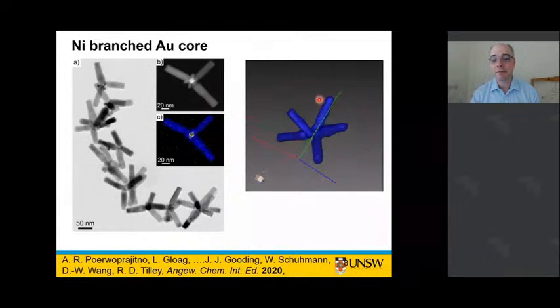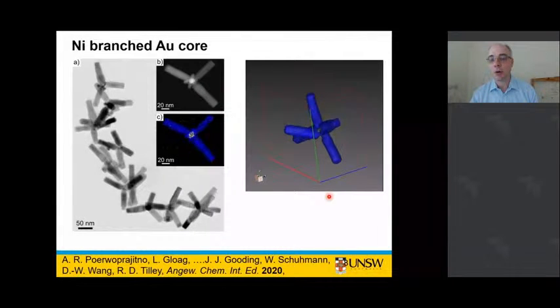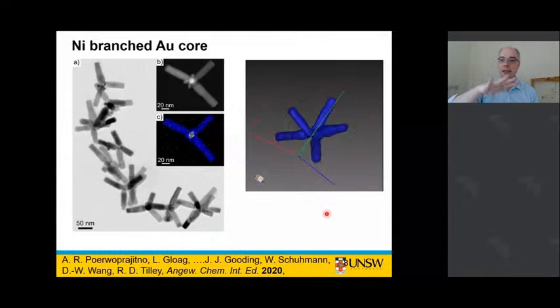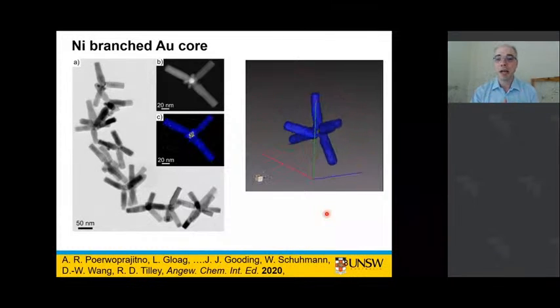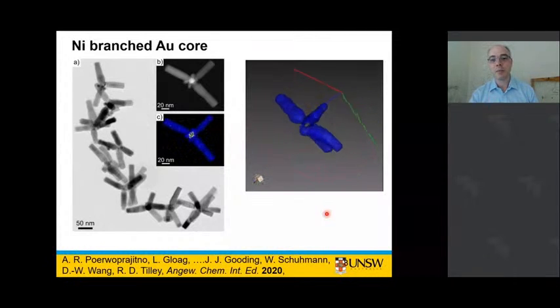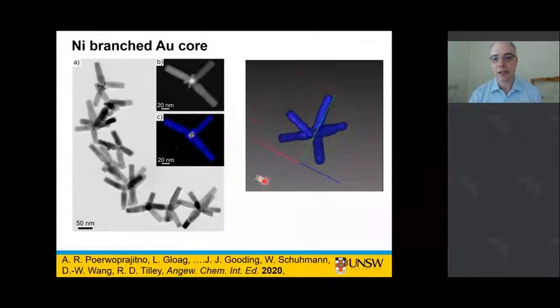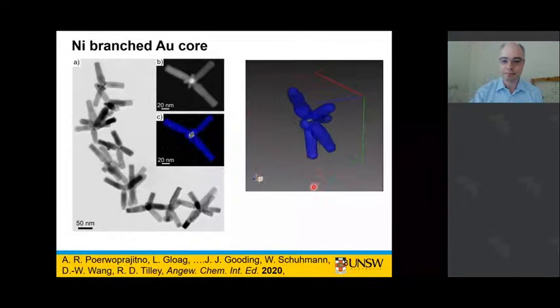And this is a video of some tomography. So this is TEM tomography, where you tilt the branch particle in the TEM, and then you can get a rendering and a structure of what the particle actually looks like in 3 dimensions. So this is one of the branch nickel structures that Agus made.